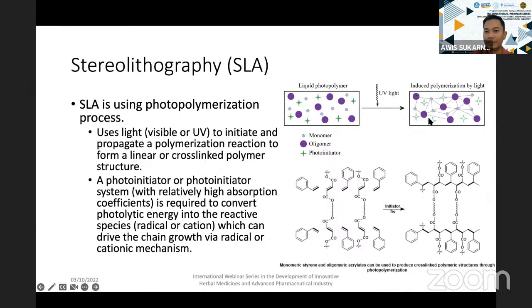So the photoinitiator basically acts to absorb the energy in order for it to induce the photopolymerization here. So once the photoinitiator absorbs it, they start to create the bond between the monomer and the oligomer here. So this one is the example of a monomeric styrene and the oligomeric acrylate. When they put it together, and then after that they add the photoinitiator. So once the photoinitiator absorbs the energy, they start to create the new bond here, and now it becomes one big polymer after being photopolymerized through the process.